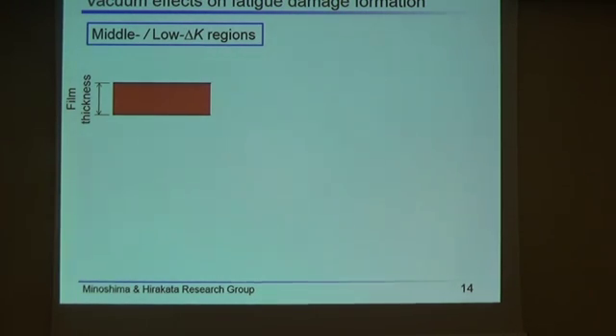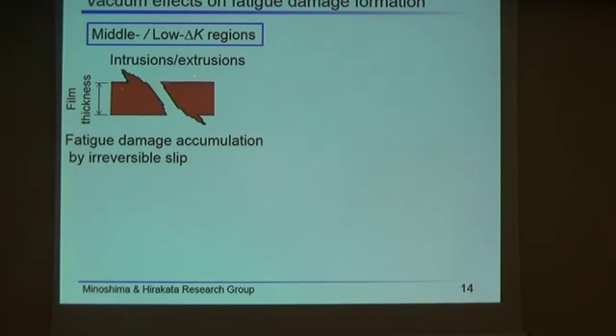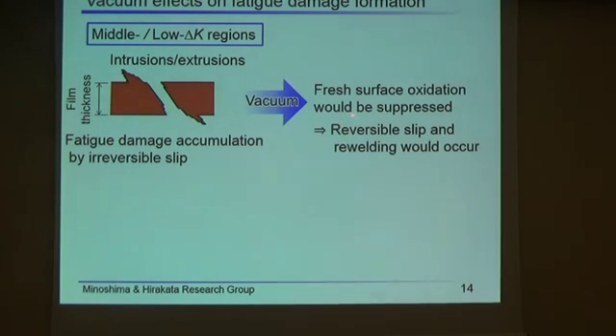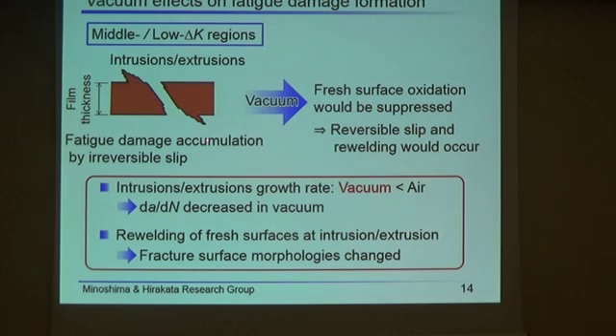In the middle and low delta K regions, fatigue crack propagation accompanied intrusions and extrusions. These intrusions and extrusions were formed by fatigue damage accumulation by irreversible slip. So, in vacuum, fresh surface oxidation would be suppressed in the intrusion and extrusion formation process. Therefore, reversible slip and rewelding would occur in the intrusions and extrusions. In these conditions, the intrusion and extrusion growth rate in the thickness direction in vacuum would decrease, and therefore da/dN decreased in vacuum. In addition, due to the rewelding of fresh surfaces at intrusions and extrusions, the fracture surface morphology changed.